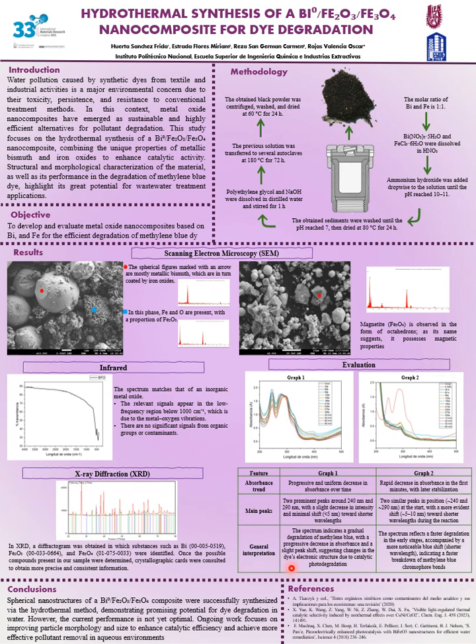Evaluation. Graph 1, Graph 2. Absorbance trend. Progressive and uniform decrease in absorbance over time. Rapid decrease in absorbance in the first minutes, with later stabilization. Main peaks. Two prominent peaks around 240 nanometers and 290 nanometers, with a slight decrease in intensity and minimal shift less than 5 nanometers toward shorter wavelengths. Two similar peaks in position, approximately 240 and approximately 290 nanometers, at the start, with a more evident shift, approximately 5 to 10 nm, toward shorter wavelengths during the reaction.